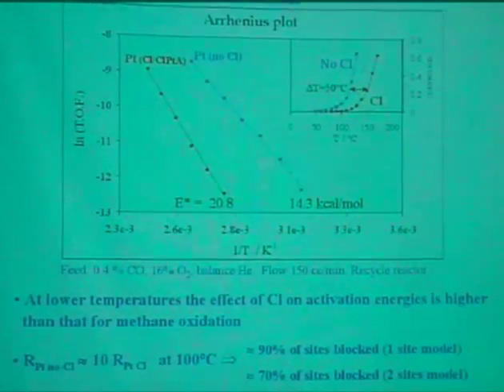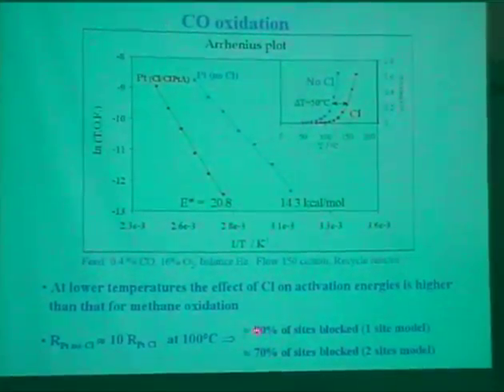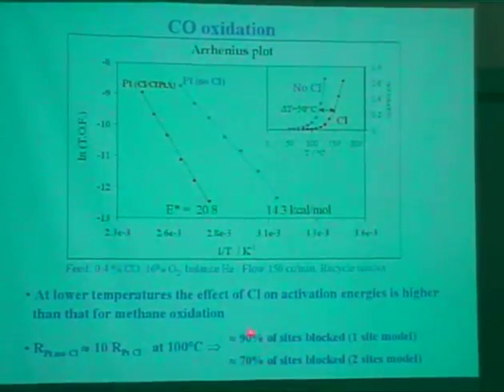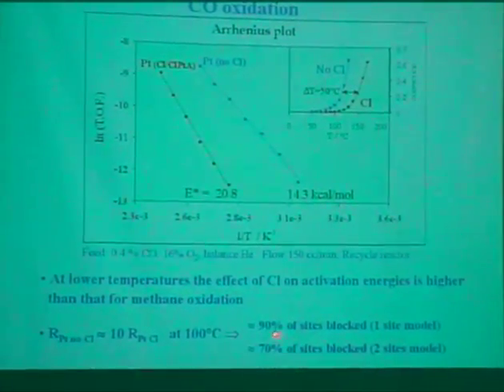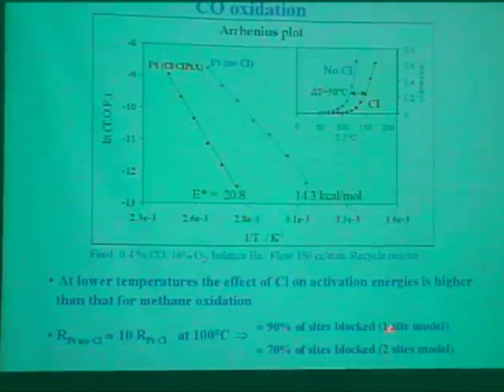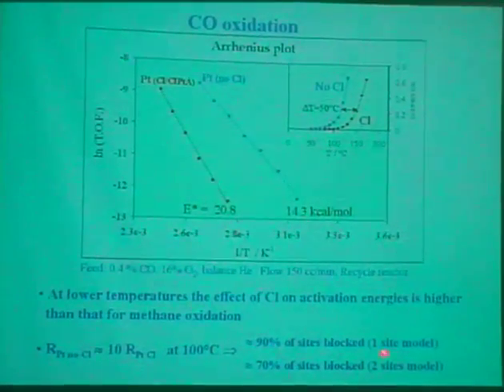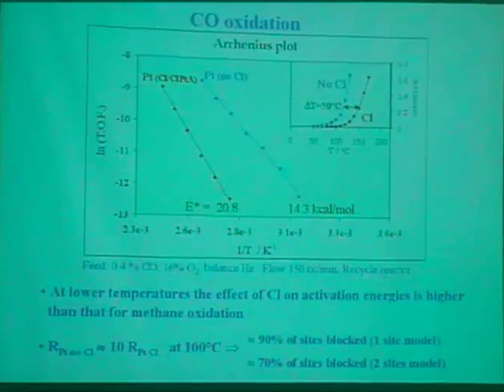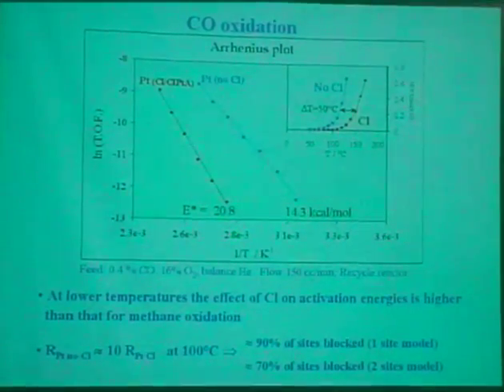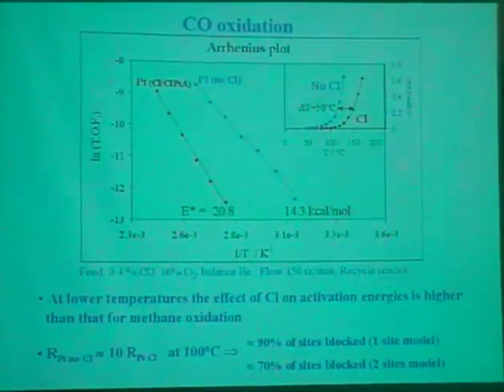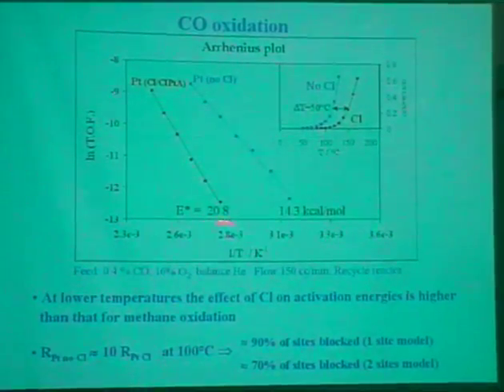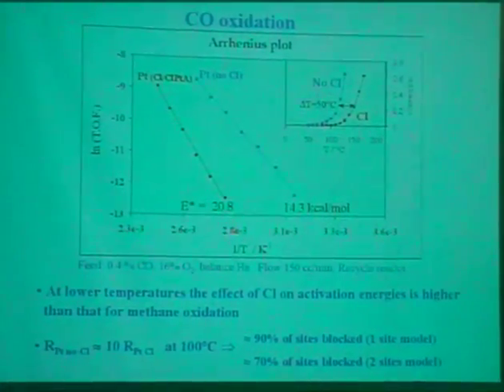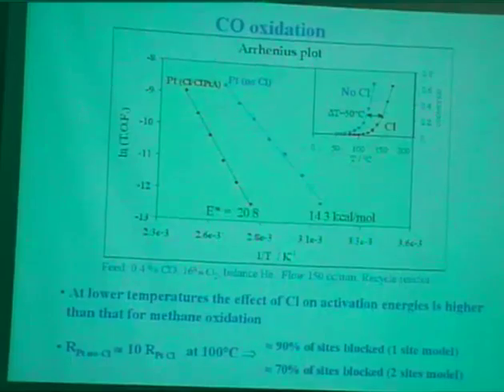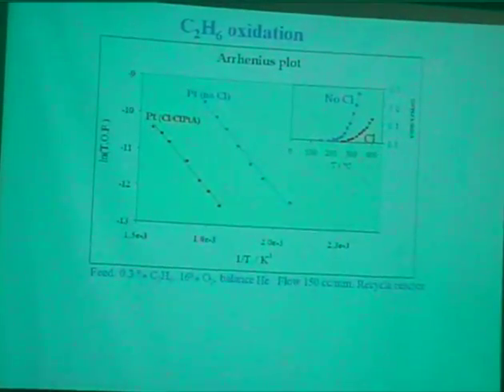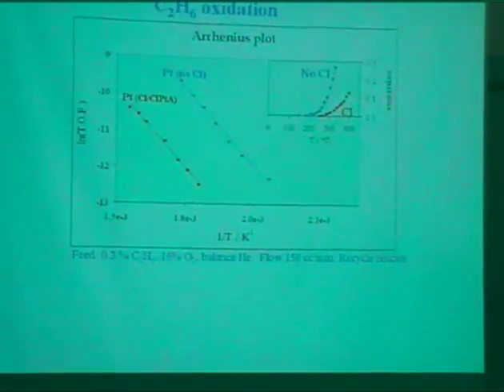We can do these calculations at high temperature. The indication, by simply looking at the change in rates, is that about 90% of the sites will be blocked by chlorine for a one-site model and 70% for a two-site model. So again, for CO oxidation, we see the same kind of behavior, except that here there's some variation in the activation energy. Not so sure about that, but then we thought, well, it's valid for CO and Cl.